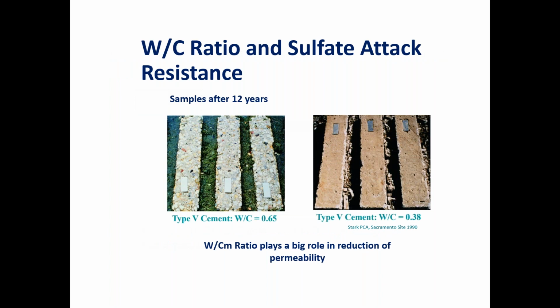Okay, we touched on water cement ratio. This is a fairly drastic contrast when it comes to the effect of water cement ratio on sulfate attack. But I promise you that even with tighter bands, say 0.4, 0.45, 0.5, you can see very substantial differences in the effect of sulfate attack based on water cement ratio. And again, that plays into the permeability of concrete. So here are field exposure concrete samples that are made with type 5 cement. In one they used a 0.38, and in one they used a 0.65. And essentially everything else is the same.